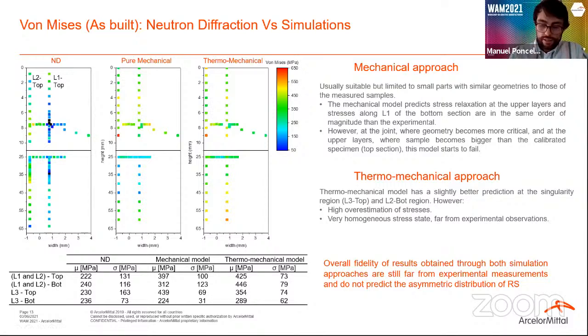Also, in an exercise with ELL, we are already working on how we can improve the experimental results to be more useful for simulations. In this study, we were assuming that the three main directions that we were measuring are aligned with the strain tensor at each point. That might not be the case. So we wanted to reconstruct the full strain tensor to better calculate the von Mises stresses at each point, and also to capture anisotropy in the part, which will be very interesting for simulations as well.